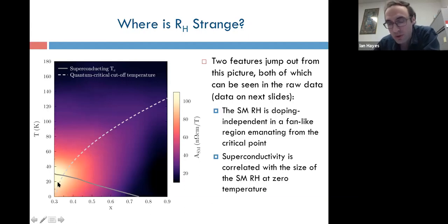That could well be true. So it's a little difficult for me to answer with the high field data because of the very limited field range available at optimal doping. So I'll show you the raw data in just a little bit. When I do the fits and try to estimate how large the strange metal RH actually is, it does top out at around 10 to 15 Kelvin or something. Okay. So that is potentially consistent with that, if you have some cutoff of about a few Kelvin in this sample.